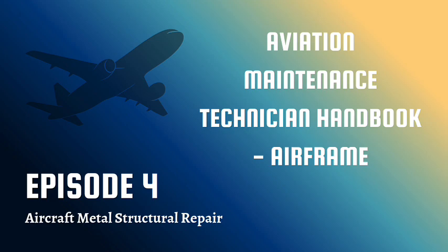Titanium. The strong, lightweight champion used in high-temp areas like firewalls or for landing gear components. Titanium is amazing stuff, about 30% stronger than steel, but only about half the weight. But it is notoriously difficult to machine, especially drilling. What makes it so hard to drill? It's very tough, and it generates a lot of heat very quickly when drilled. You absolutely need very sharp drill bits, usually made of carbide or high cobalt steel, like 8% cobalt. And similar to CRES, the technique is crucial. Very low speed and very high constant feed pressure. We're talking maybe 50 pounds of force pushing down just for a small number 30 drill bit. 50 pounds. Why so much force?